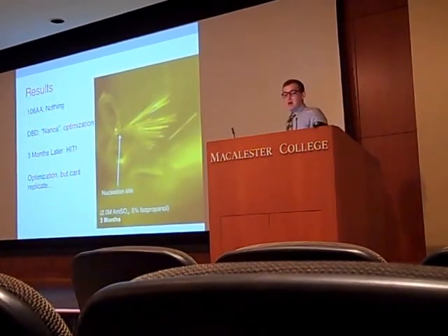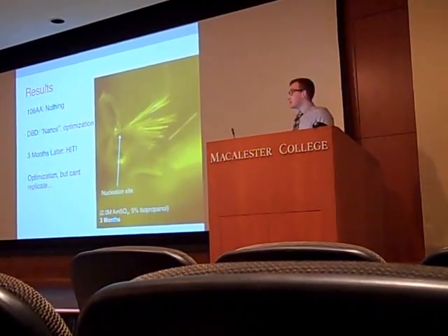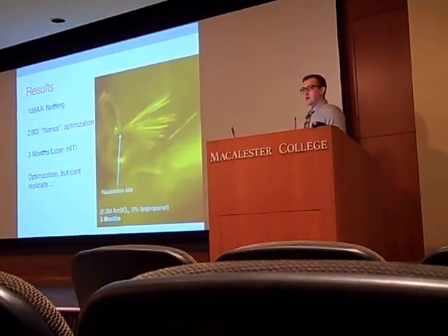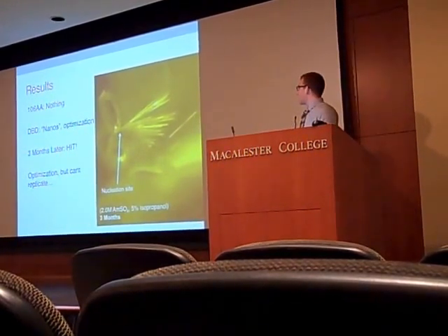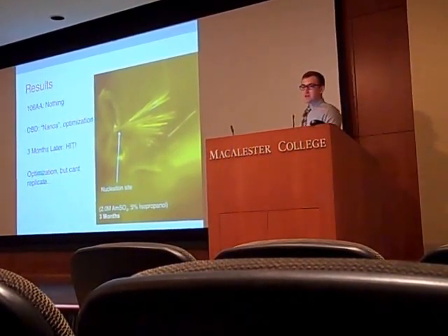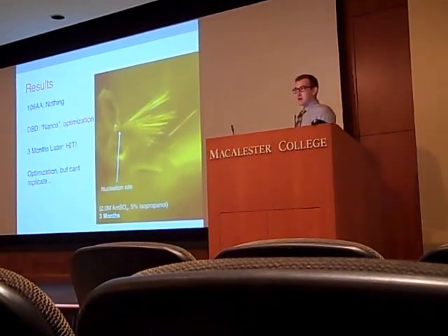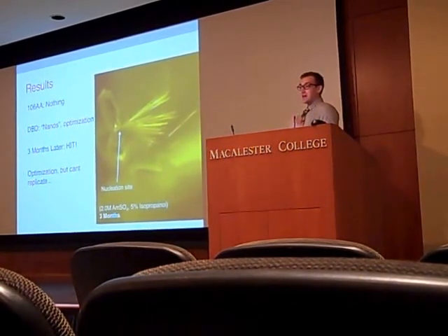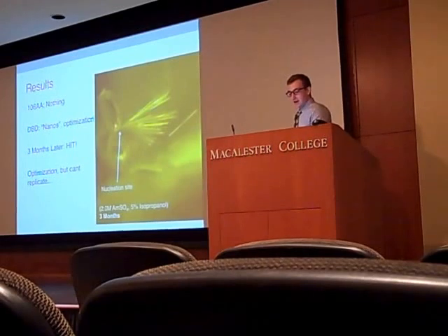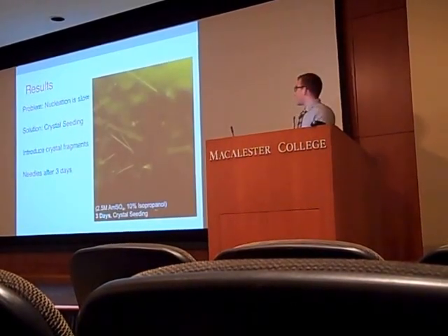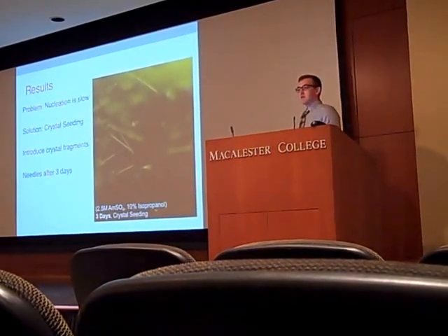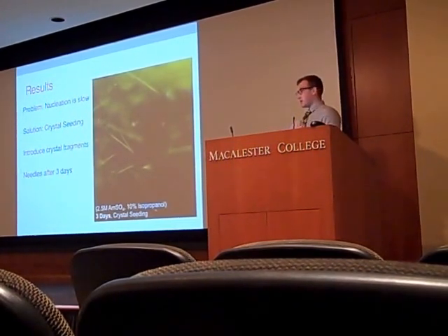So naturally, I go to optimize on this crystal, but no matter what I do, I can't get anything to grow, even in the exact same conditions. So what's going on? I talked to Marcos, and we, or I should say he, concluded that the problem was with nucleation. Because we didn't see anything grow for 3 months, but then once it did appear, it grew very quickly. A whole bunch of needles came out of that nucleation site. It was nucleation that was the slow process.